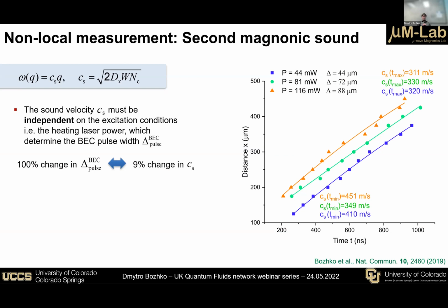And moreover, when we fit our experimental data, we can see that the starting and the final velocities are very different. So indeed, these curves are not linear; they are parabolic. They are sort of square root dependence of the condensate density.